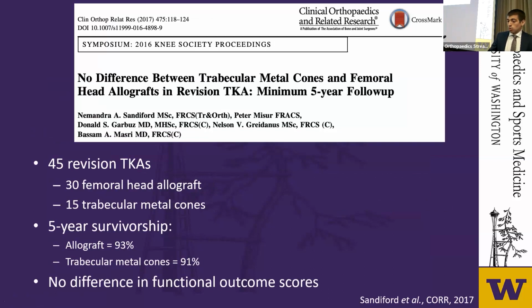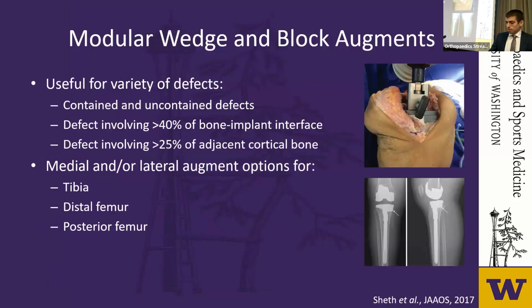This is in contrast to a more recent 2017 study published in CORR that did look at a relatively small cohort of 45 revision total knees, 2/3 of which were treated with femoral head allograft, 1/3 of which was treated with cones. And they found a comparable rate of 5-year survivorship between the allografts and the cones. These authors suggesting, in contrast to the prior study, that maybe in fact bulk allograft is a viable option in these patients.